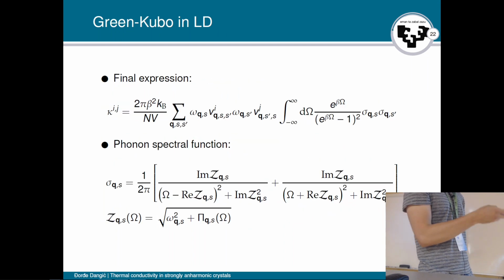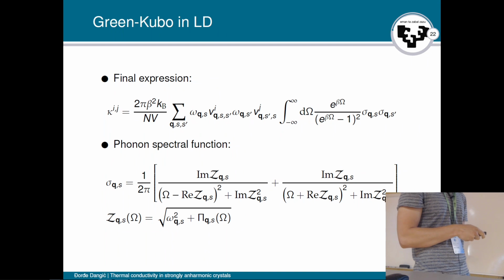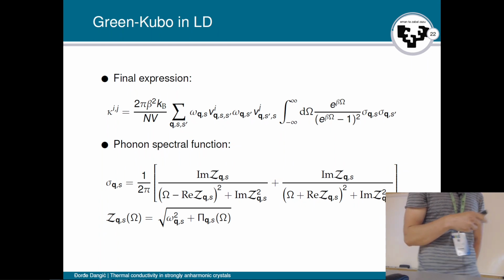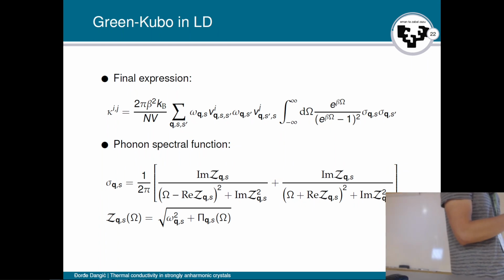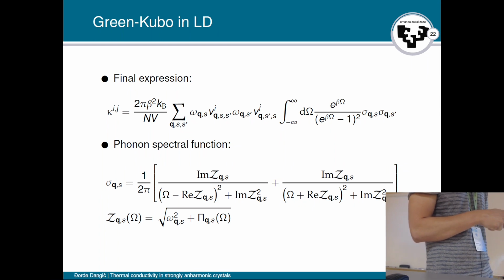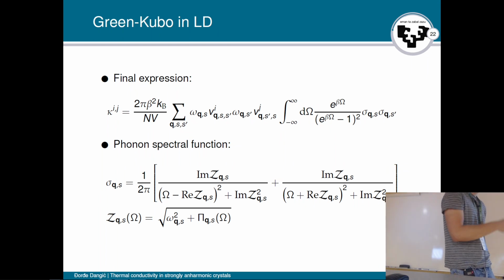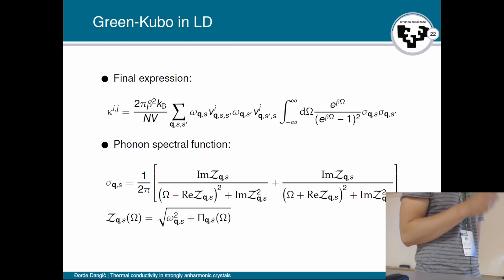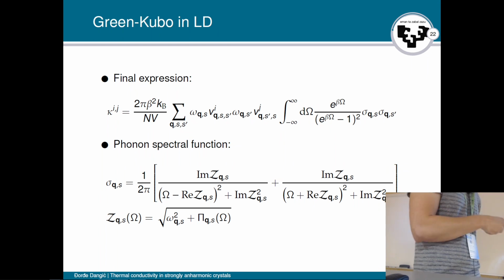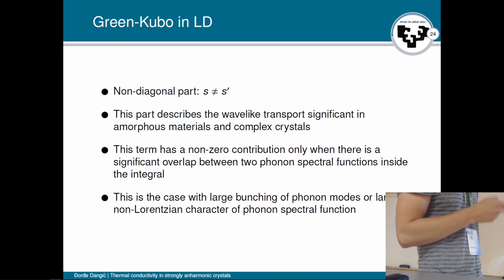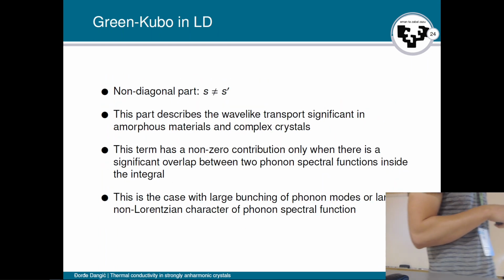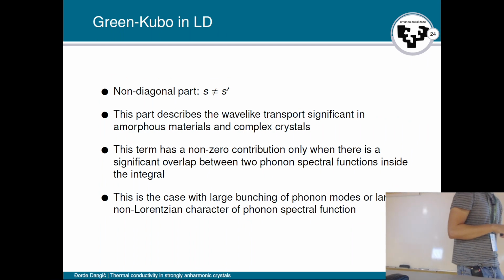But we can see that in the case that s and s prime are different, this integral will have a contribution only if there is a significant overlap between the phonon spectral functions. And when can we expect a large overlap? At least either when the phonon spectral functions are very broad, so they spread over a large frequency range, or they are very close together. So we can expect it either when we have a bunching, which is in these complex crystals and amorphous materials, or when we have highly anharmonic materials. Okay? So this is what I said. We can expect this type of transport to have a contribution when there is a large bunching of phonon modes or large non-Lorentzian or large broadening of the phonon spectral lines.